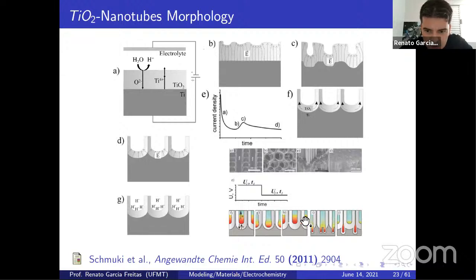It's a finite element method used to study. So here the guys used a larger voltage, like here, and took a short one to a small voltage like this one. And we have a split of this part here. It's very interesting, very useful for batteries and supercapacitors because we have the blocked surface. If you block the surface, we can make the extraction of the lithium or the sulfate, or whatever the counter ion is, most difficult. So we increase the time of discharge like this here. If you take a look, all this part here was a pulse of voltage, and we can obtain a process like this one and put the mesh together, and it became quite difficult for lithium to get inside and get outside from the surface.